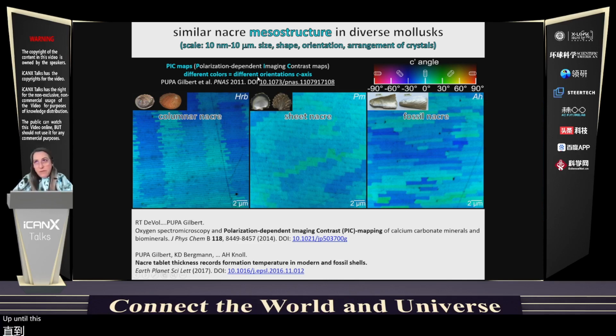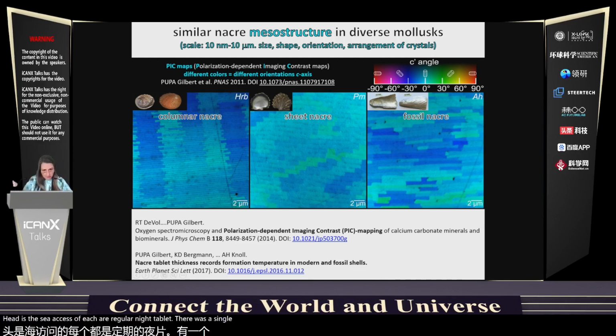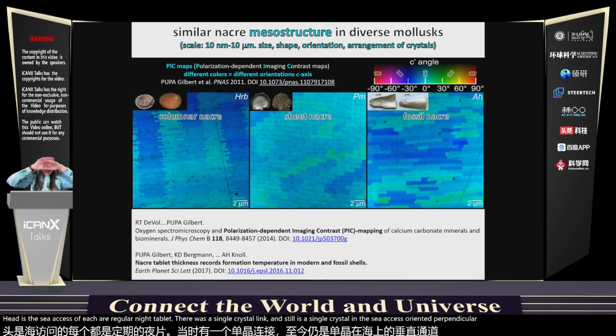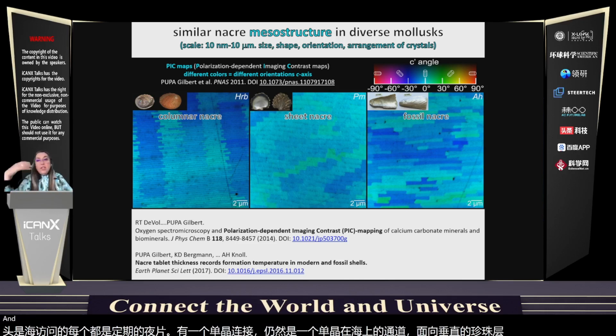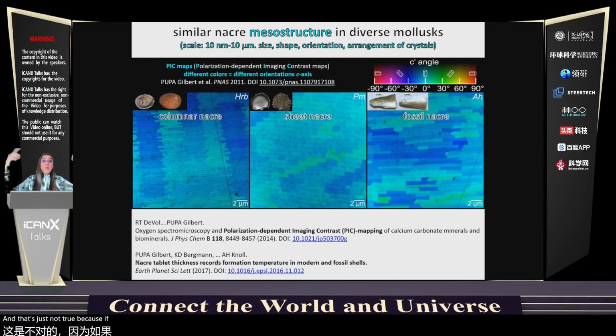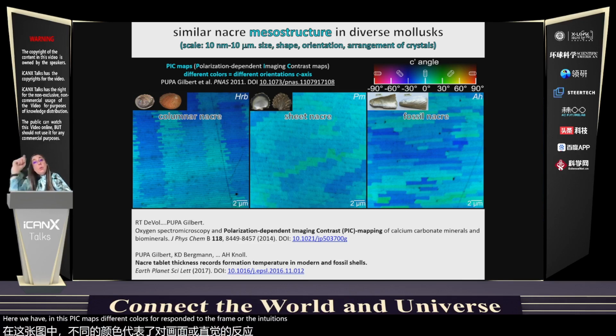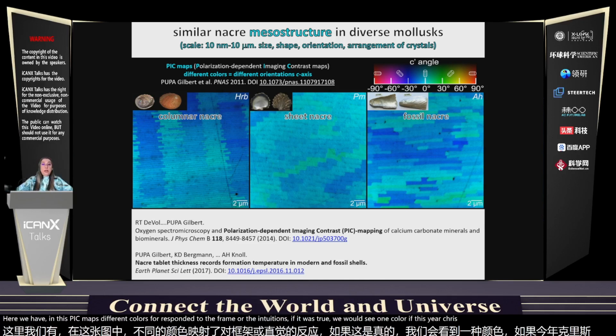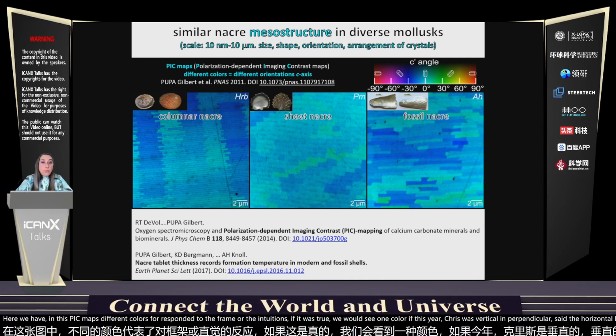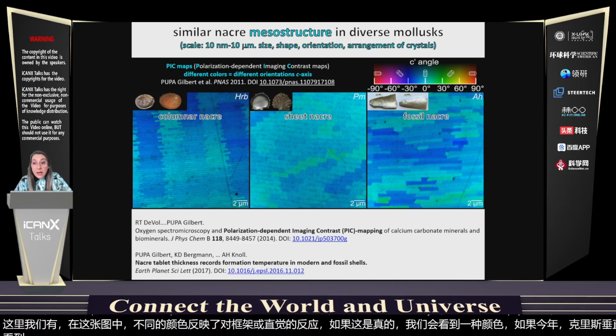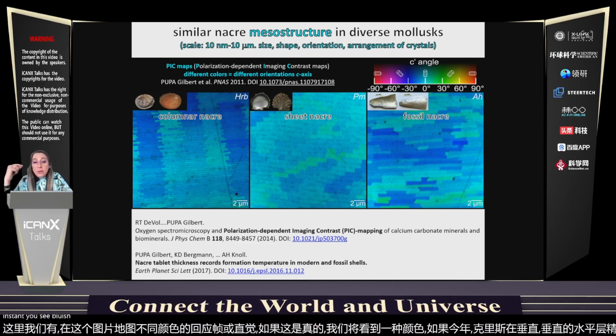Up until this work, everybody said that in nacre, the z-axis of each aragonite tablet was a single crystalline, it still is a single crystalline, with the z-axis oriented perpendicular to the nacre layers. And that's just not true, because if that was true, here in these PIC maps we have different colors corresponding to different orientations. If it was true, we would see one color. If the z-axis was vertical and perpendicular to the horizontal layers in all images, all you would see is cyan. But instead, you see bluish cyan to greenish cyan.